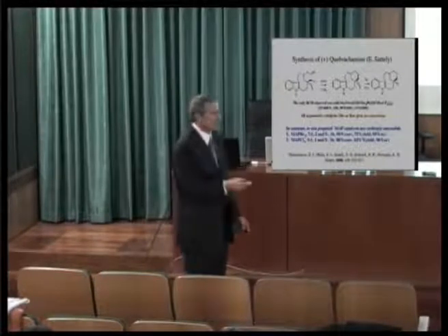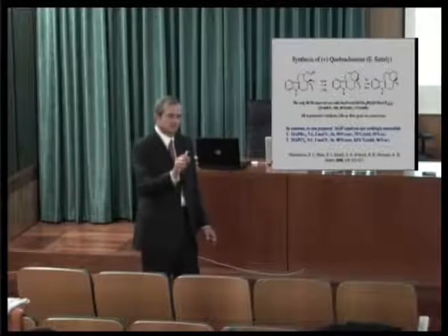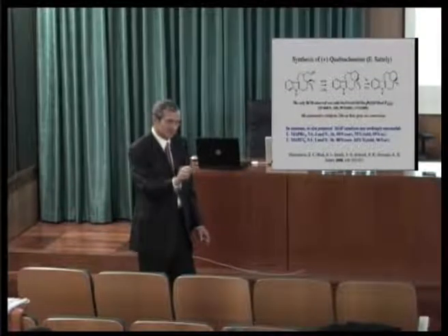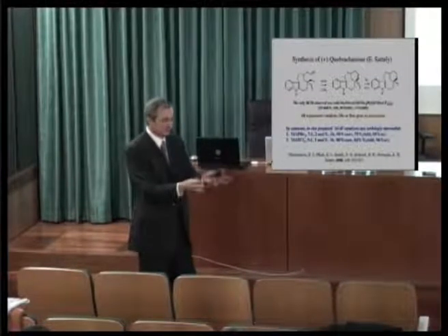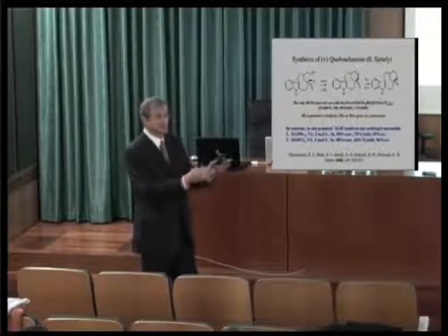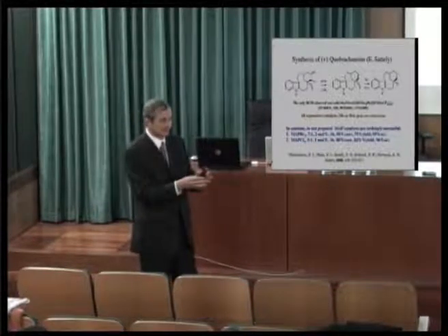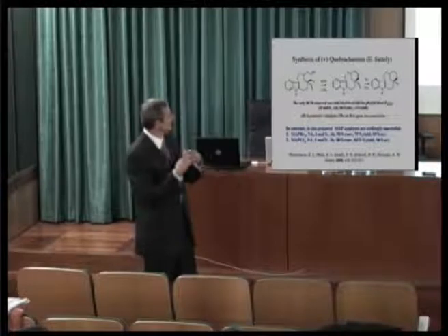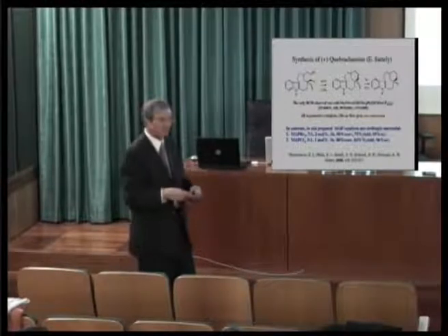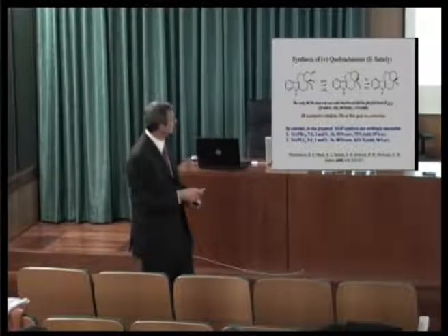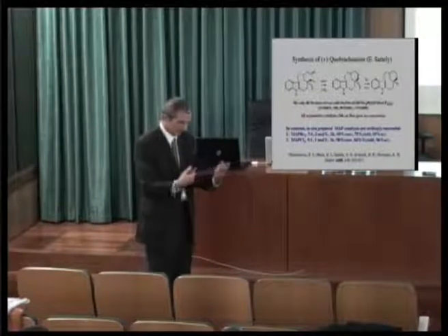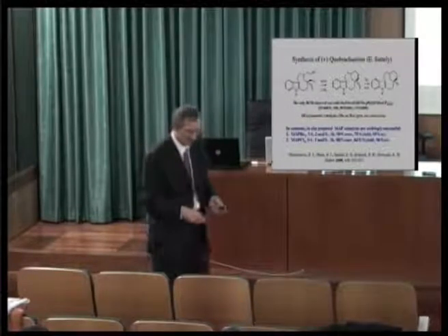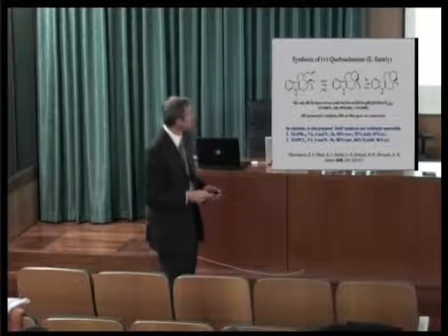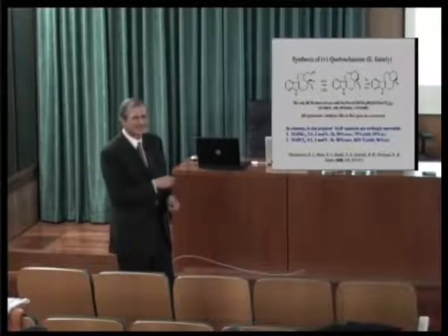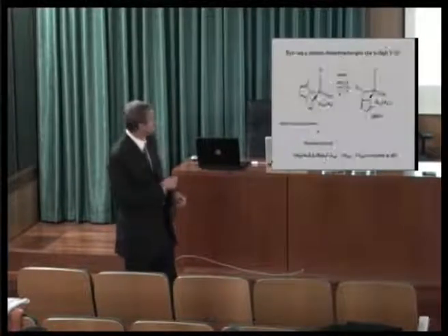Because if you have 2 diastereomers, if you have 2 different chiralities at the metal center, as some mixture, let's say 2 to 1, the mixture that I showed you, 7 to 1, is actually the kinetic mixture, not the thermodynamic mixture. Thermodynamic mixture is about 2 to 1. Then you should get these 2 counteracting one another and not giving such a high ee. So how does such a high ee arise?